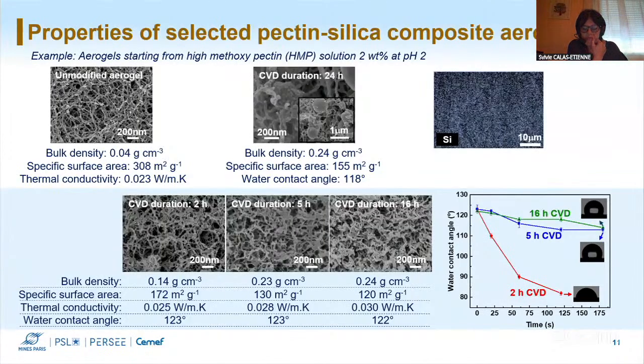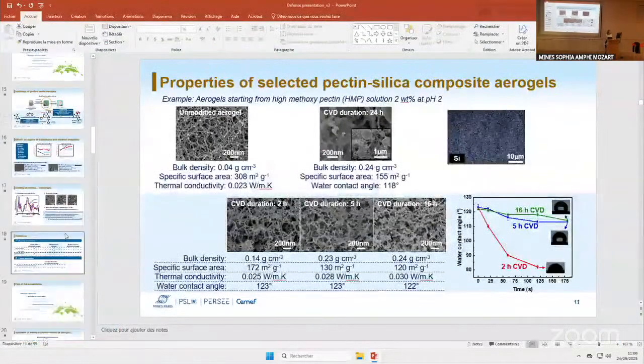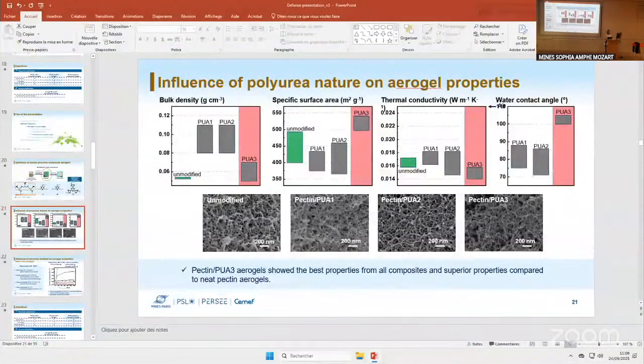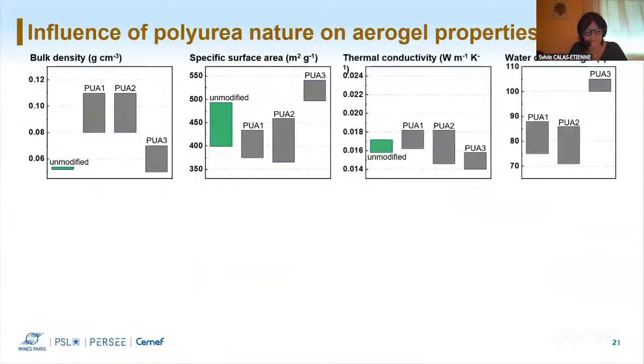just first question, why does the addition of polyurea sometimes reduce the thermal conductivity compared to pure pectin, even if the density is almost the same and even slightly higher? Do you know why? Yes, we have some idea for this. So as I discussed before, we think that when we add polyurea in our material, during drying we don't have a closure of very small pores. So for this reason, we think that we have higher surface area and lower thermal conductivity. Okay, just the surface. Okay.